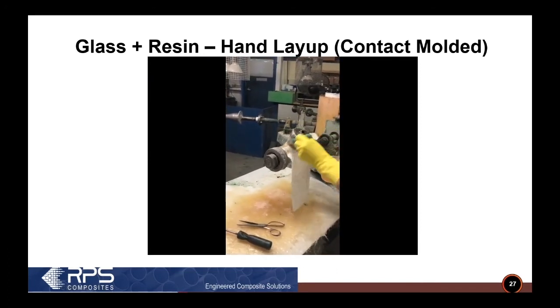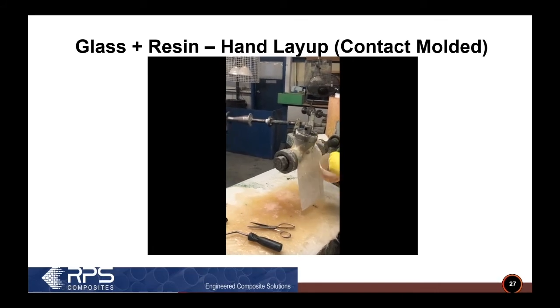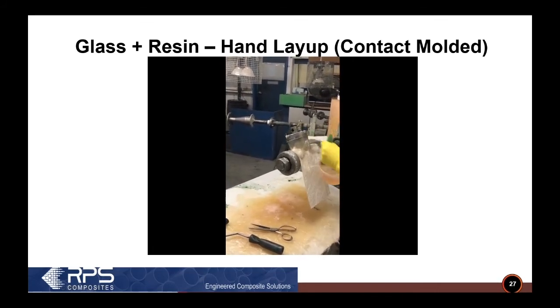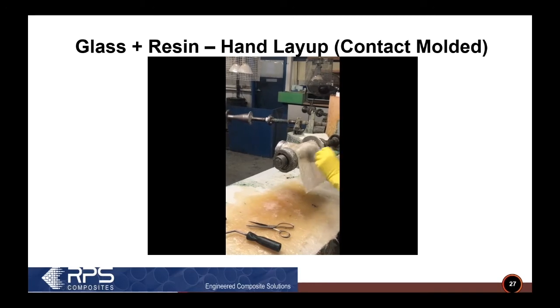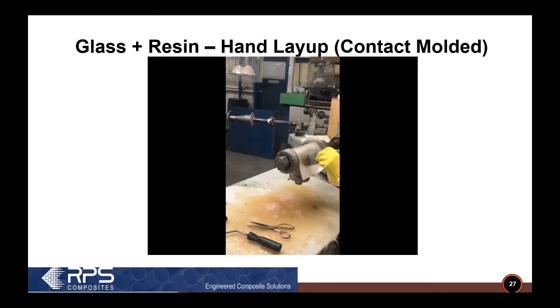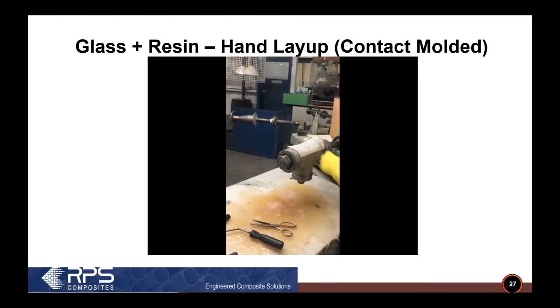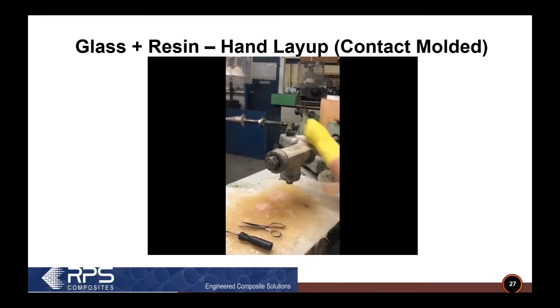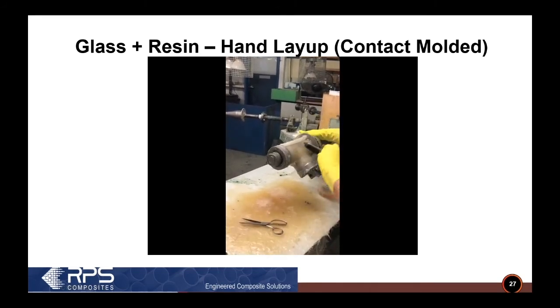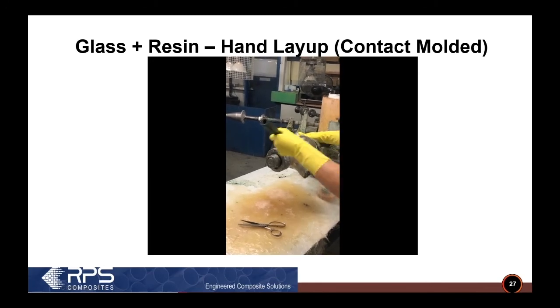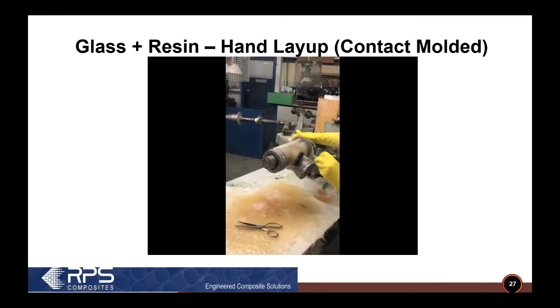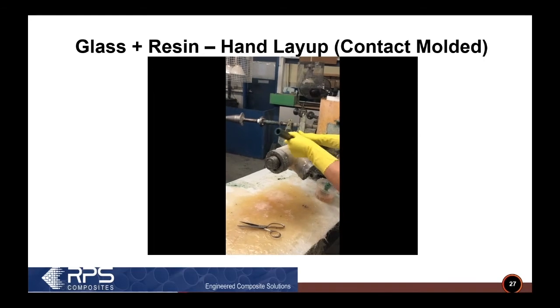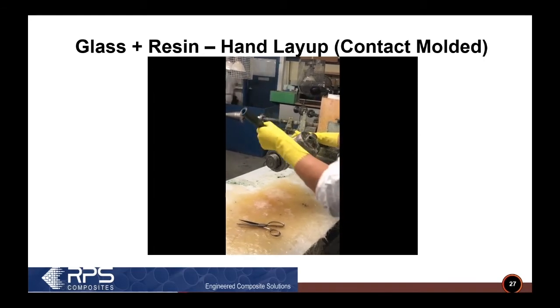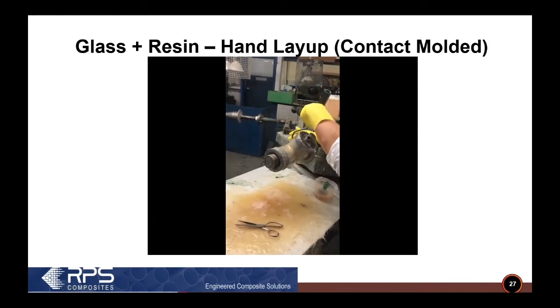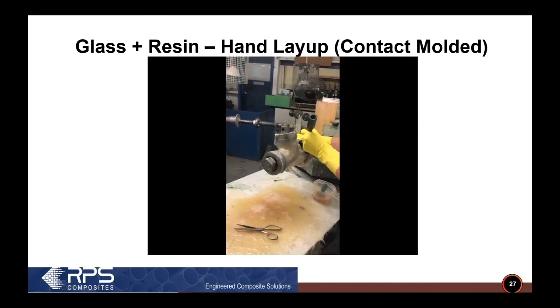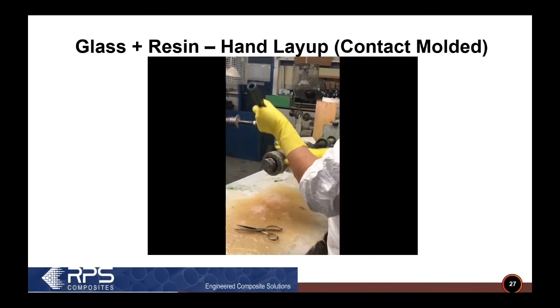So here's a technician making a tee. The technician would have been told to use this particular style of resin and this particular catalyst. It would be pre-mixed for them. The technician would catalyze the resin depending on the temperature and the size of the item they're working on. Then they saturate the glass reinforcement and apply that saturated glass reinforcement to the mold. And what you're seeing now is the technician rolling out all the air that's in the laminate.